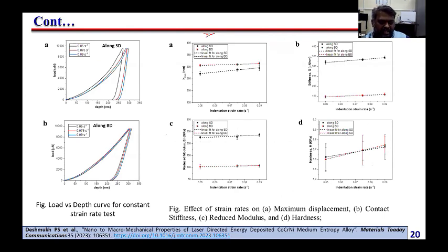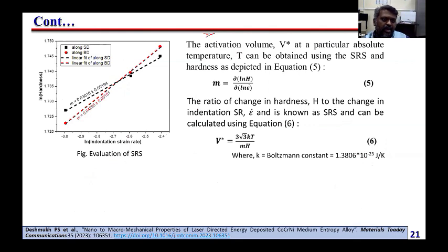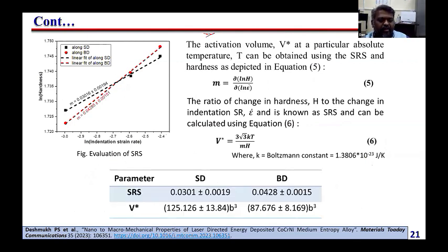We also varied the strain rate in the hardness tests and did not see much difference. The strain rate sensitivity is very low, 0.04 or 0.03, which is very typical for this multi-component alloy. Multi-component alloys usually show very low strain rate sensitivity and very small activation volume. Conventional alloys have an activation volume in the range of thousands of b cubed, but for a high entropy alloy it is in the range of 100. That is what we observed in this medium entropy alloy also.